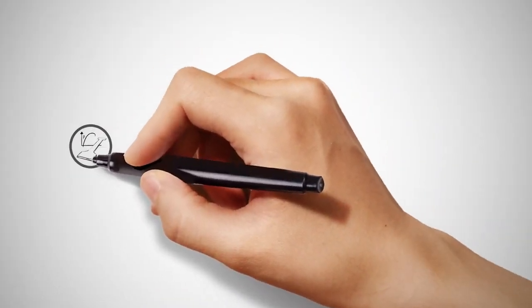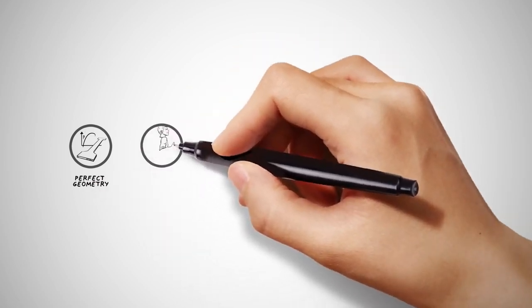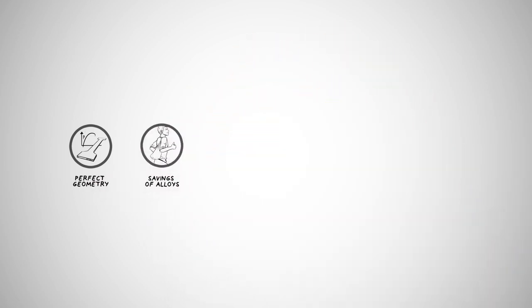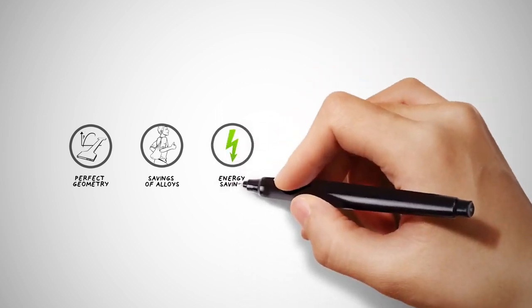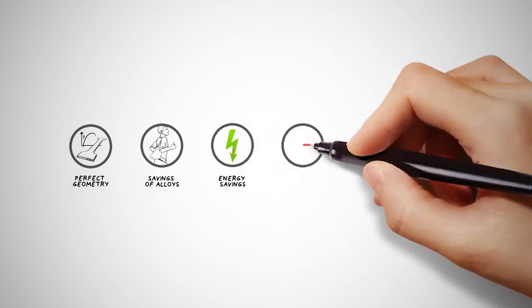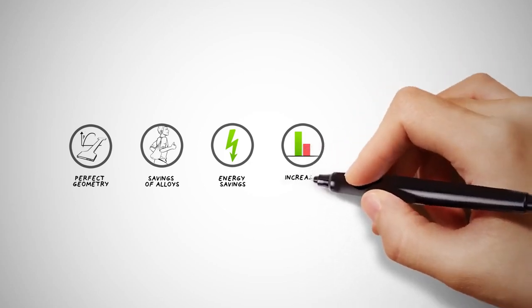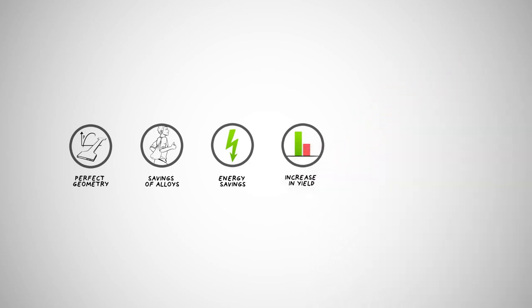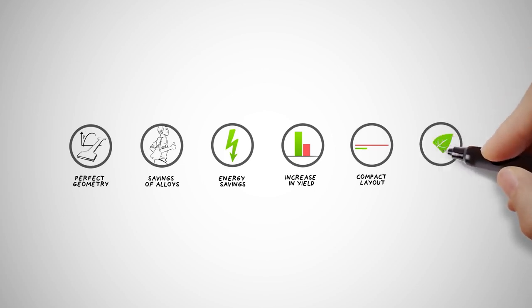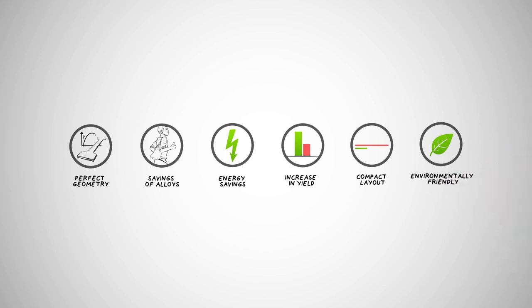And what's the bottom line? Firstly, perfect geometry. Secondly, immense savings of expensive alloying elements. Thirdly, sizable energy savings. Fourthly, an increase in yield of over 98% from the liquid steel to good coil, as rolling is endless and avoids head and tail losses. Not to forget a drastic reduction in overall turnkey investment owing to the line's compact layout and length of only 180 meters. And finally, the clearly positive environmental aspects.